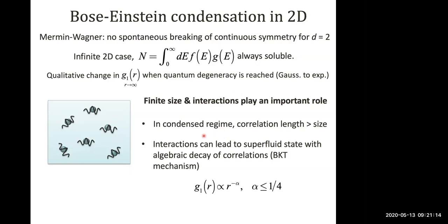And we also have interactions. So interactions also play an important role in 3D. And in 2D, they can lead to a superfluid state where the decrease in the first order coherence becomes algebraic. And this occurs due to the Berezinskii-Kosterlitz-Thouless mechanism beyond some critical density, which is related to the strength of these interactions.